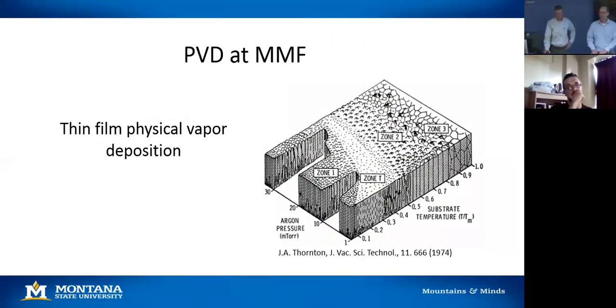So this is basically the structure of the film as it's growing on a substrate. Once you get over about 100 nanometers, you get these kinds of film structures. Some of them are very porous and have a lot of voids. Some grow together in more of a polycrystalline amalgam, I guess you call it. As you go to higher and higher temperatures, you get more crystalline growth. It has to do with the deposition parameters, the energies of the atoms hitting the substrate, and the temperature of the film as it's growing.